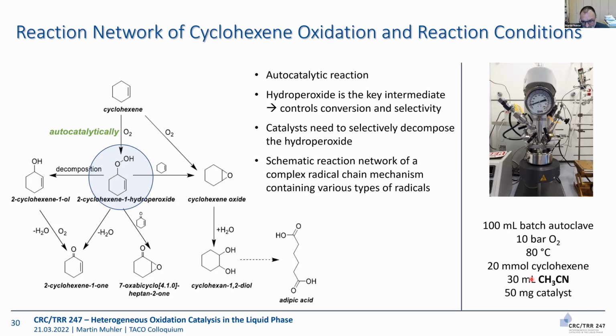Okay, then I will come to a rapid end. Then I will give you just a little bit of a flavor what then the real challenges are when we really work in the liquid phase, and not just with 2-propanol as a probe molecule, but with molecules that are really of chemical interest, even in chemical industry. And the molecule we oxidize is cyclohexene, and we do it now using acetonitrile as solvent. That means we dissolve cyclohexene in acetonitrile. We work in an autoclave. You see it here again. We pressurize with oxygen, and we don't go to too high temperatures for reasons I will show you in a minute.